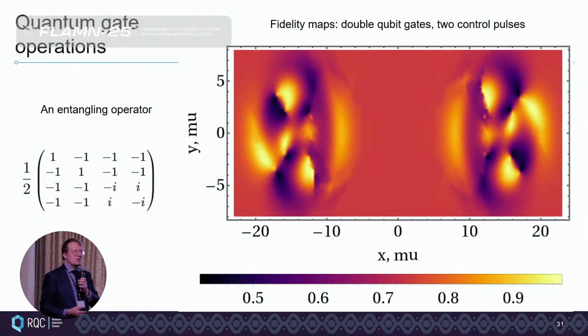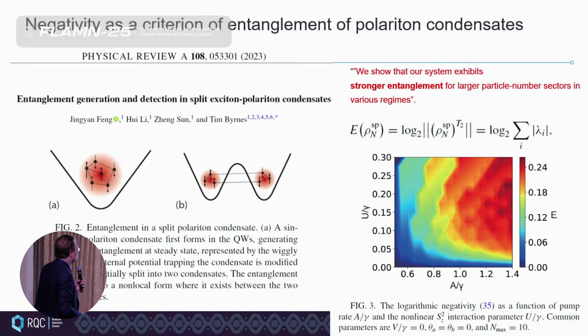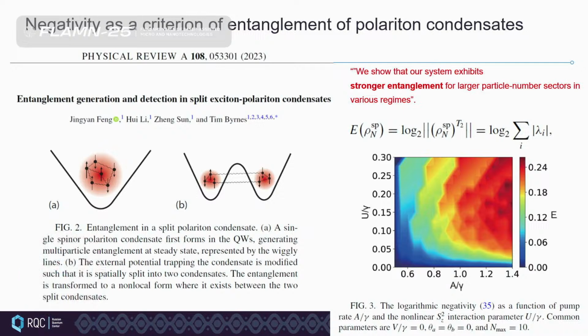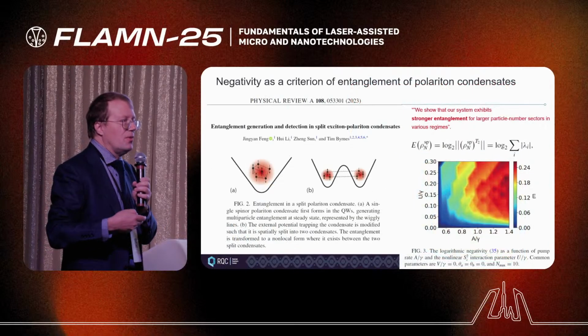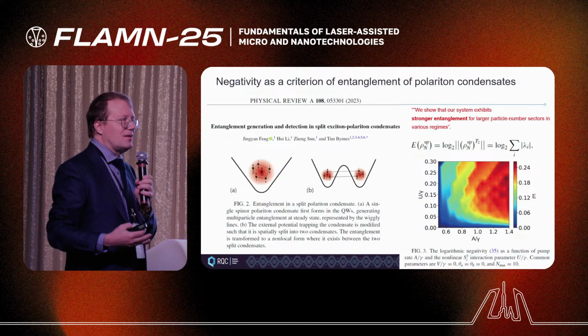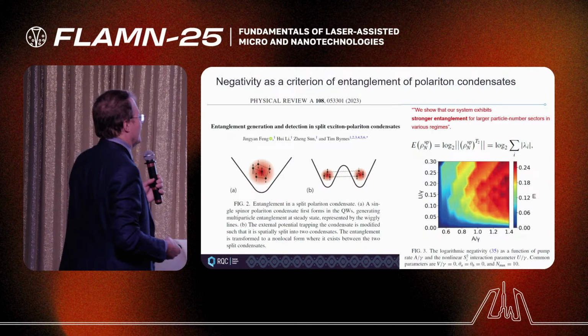So after all these discussions, we really decided to put in an effort. We studied this entangling operator that moves our state from a pure state to an entangled state. We read a lot of papers on the entanglement of bosonic condensates, including bosonic condensates of exciton polaritons. And we concluded that, again, counterintuitively, surprisingly, the more particles you have in the condensate, the better it is for entanglement. When you have many particles, it does not break coherence, it doesn't break entanglement, but it strengthens entanglement.